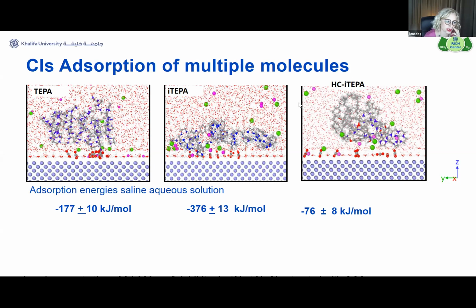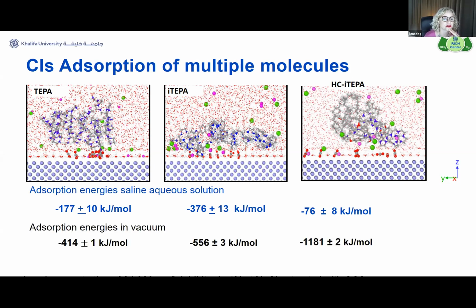And then we calculated the adsorption energies when we have the saline aqueous solution. And when we compare this with the energies in vacuum, we can see, of course, they are much lower because of the effect of the environment. But interestingly, we see that in this case, the one with the better adsorption is the iTEPA, the one that doesn't have the alkyl chain.